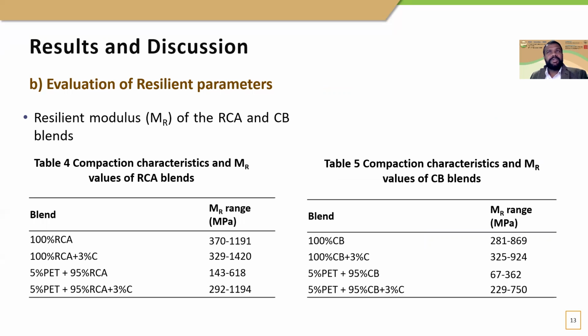The RCA blend shows higher resilient modulus values than the CB under the same confining pressure applied at 15 stages of the RLT test, or the repeated load triaxial test. Resilient modulus values of the stabilized materials are highly governed by the Los Angeles abrasion loss value of the materials used. CB shows a higher finer particle percentage and flakiness index value than RCA. Materials which have particles with high flakiness index and high finer percentages increase the surface area of the total material mixture. Such samples in stabilized conditions require more cement volume per contact material grains for the same cement content, hence resulting in low resilient modulus values.